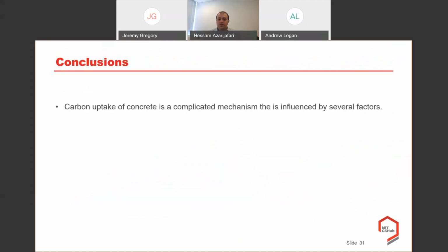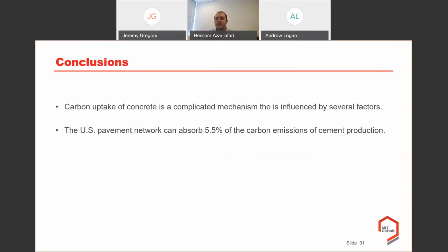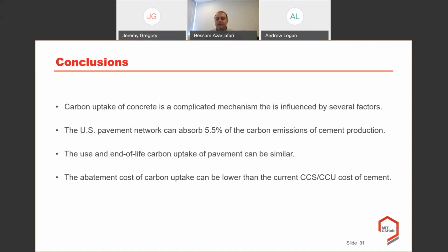So let's go to the conclusion. First of all, we found that the carbon uptake of concrete is a complicated mechanism, and it's influenced by several factors: the binder, and external factors like environment. The second one, the US pavement network can absorb around 5% of the carbon emissions from the cement production. The total amount of those whisker plot chart corresponds to 5% of the total cement production emissions that we calculated. The use and end-of-life carbon uptake of concrete pavement network can be quite similar and in the same range. And at the end, the abatement cost of carbon uptake can be lower than the current CCS or CCU cost of cement, those technologies that are implemented on the cement and concrete industry.